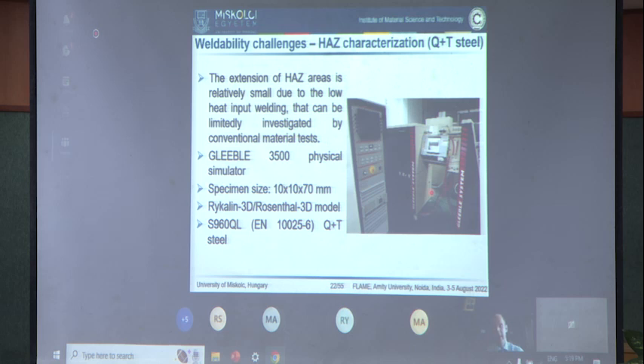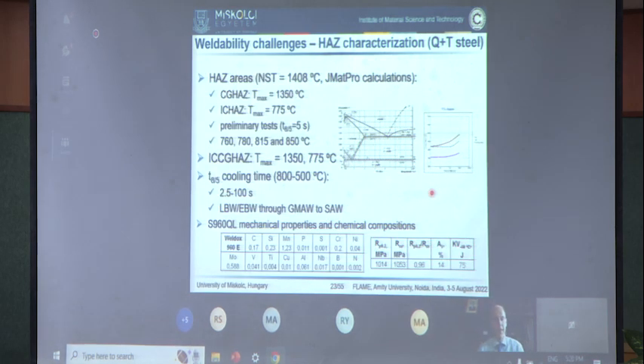But with this kind of equipment and its resistance heating system and cooling device, we can realize the welding heat cycles, and we can homogeneously produce the desired heat-affected zone based on different heat cycle models, such as Rykalin's 3D and Rosenthal's 3D. During our experimental work, we analyzed the heat-affected zone characteristics of this 960 quenched and tempered steel.